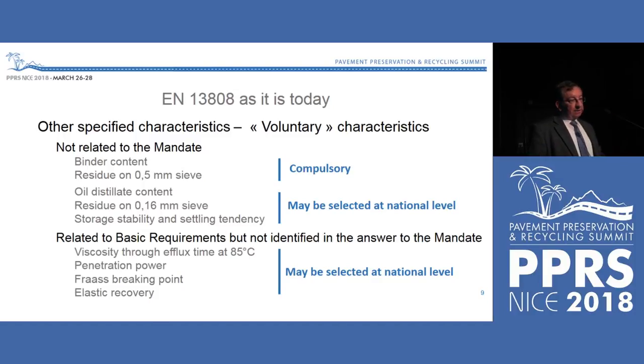Besides those essential characteristics, the EN 13808 standard also includes so-called voluntary characteristics, of which some are not directly related to the mandate, even if they may be compulsory, like binder content or sieve residue. Others may be just selected at a national level, such as storage stability and settling tendency. And funnily enough, there are also some voluntary characteristics which have been introduced and which in fact should be related to basic requirements, even if they have not been identified in the answer to the mandate. That's, for instance, the case for low temperature behavior like Fraass breaking point or cohesion, or like elastic recovery.